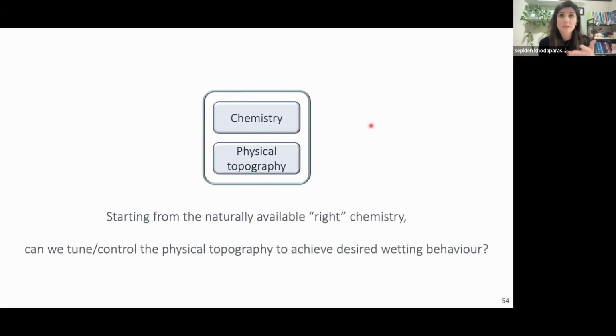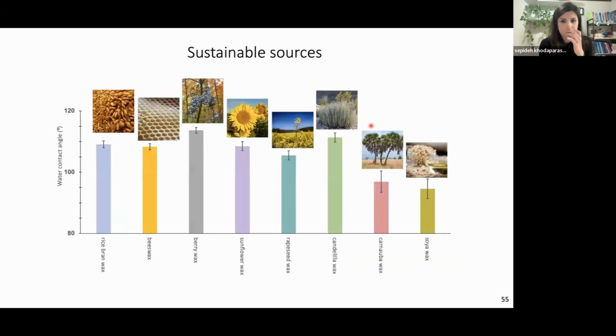And we wanted to pick up similar chemistries, because these are already chemistries that are hydrophobic, but you add the structure to it, so you get superhydrophobicity. But in nature, normally this is done by tuning the chemistry. So every time you want to get a new physical topography, you change the chemistry. Our main objective was, can we keep the chemistry constant and do some physical manipulation and change the environmental conditions and the kinetics of phase change and crystallization to be able to change the physical topographies, and then look at how the physical topography controls the wetting behavior.